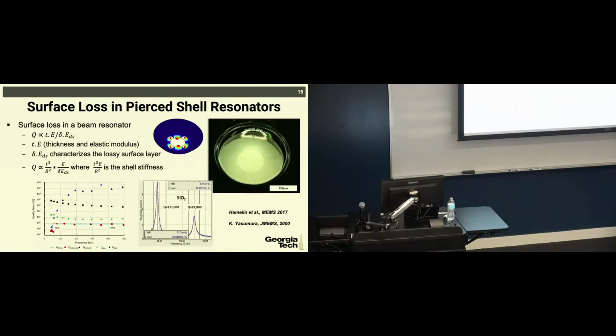And what he saw was that as he changed the dimension of this device, and these red dots are what he was measuring, as the frequency changed, the Q did not change. The Q stayed at around 100,000, as is shown here. So that pointed to the fact that these devices are all surface loss limited in terms of dissipation mechanism, because that is a mechanism that doesn't scale with the dimensions or the frequency of the resonator, okay? And you can see that all other types of losses are going to be creating Q factors that are much larger than what we measured.